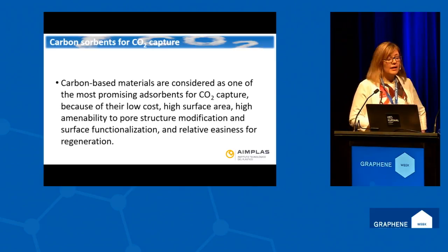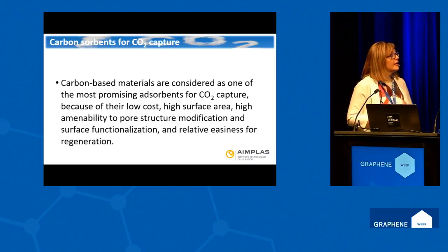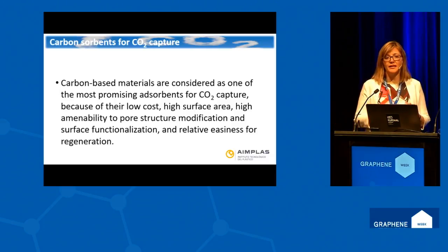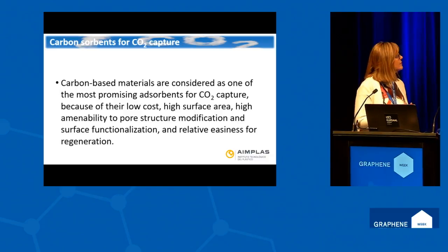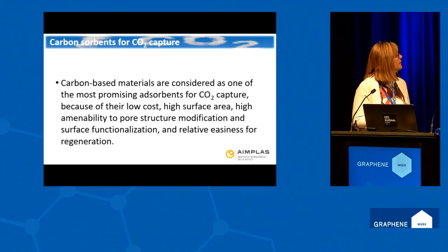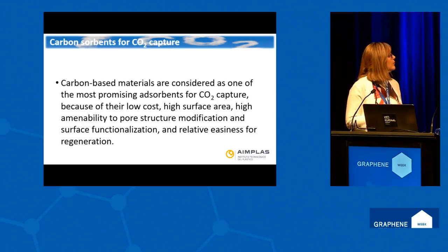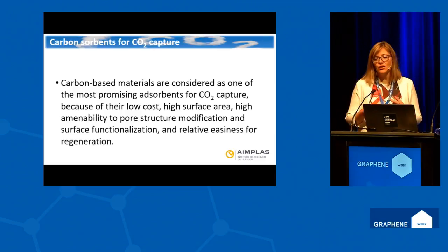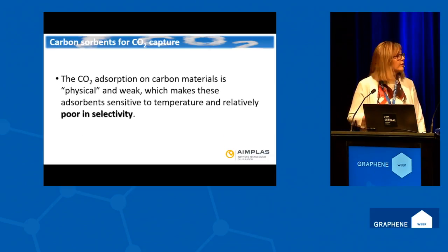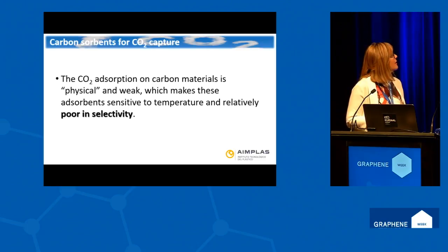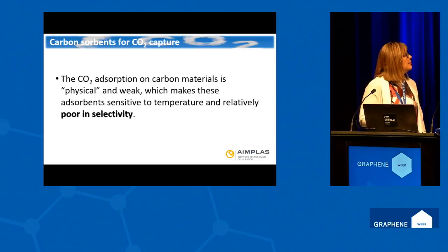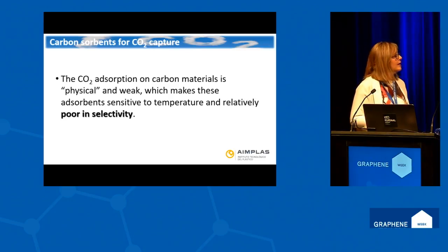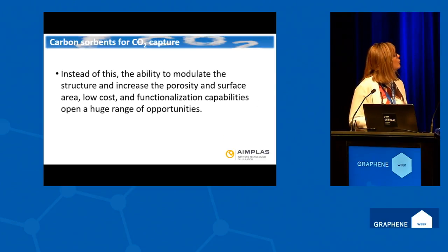Carbon-based materials have low cost, high surface area. We can modulate the structure and the porosity of this material, so we can customize these sorbents in order to obtain the highest effectivity, and we can functionalize these carbon structures. And relatively, the regeneration of this structure is easier compared with another. What is the problem using this type of sorbents? Mainly the relative selectivity and the temperature, but we can solve it by modulating and functionalizing the surface of these materials. So we can have a lot of opportunities to use in different areas.